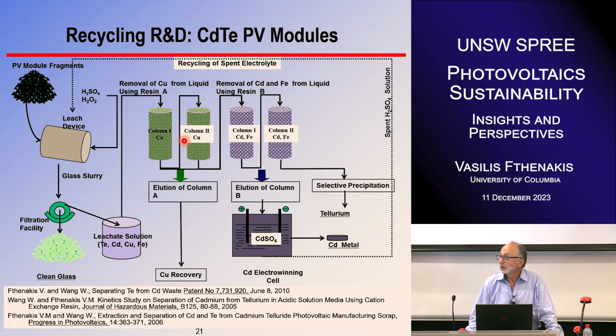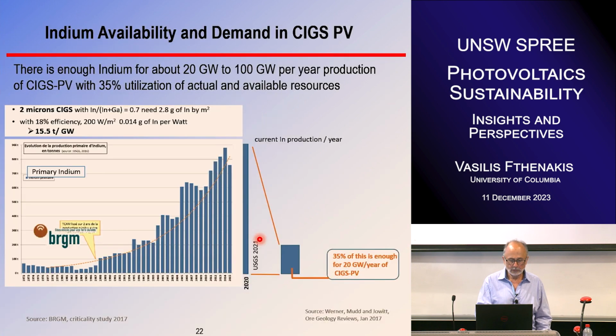The first will retain copper, the second will retain cadmium. At the end you have a leachate rich in tellurium, which precipitates as tellurium dioxide. You rinse the ion exchange columns and you get copper from the first and cadmium from the second. You have to go through purification if it's not really 6 nines, and the formation of cadmium telluride. We actually found that this could be done at 1 cent per watt years back. Today it could be even less because you have more watts per module.